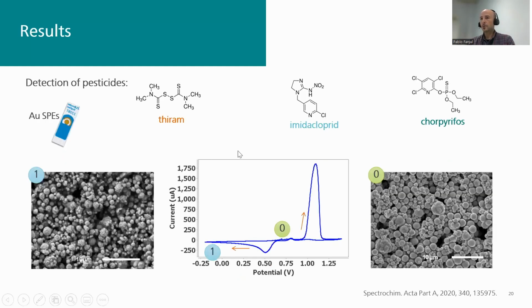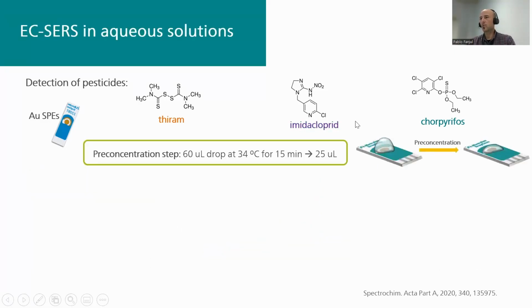I will show you another example, but in this case with the gold material, because the previous one with the ruthenium bipyridine was made with silver. So in this case, it's for detection of some pesticides: thiram, imidacloprid, chlorpyrifos. Initially, we have this gold surface and we don't have any Raman spectra, but after the oxidation of the gold and after the reduction of the gold, and once we have this surface in our metallic electrode, is when we can get the Raman spectra of the different molecules.